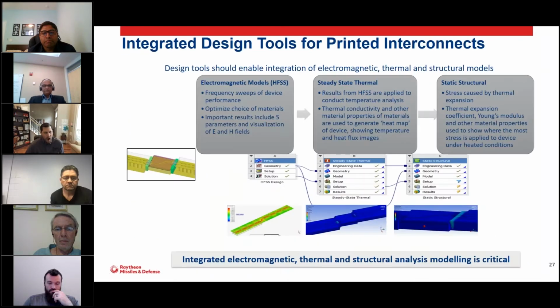And then once we've done that, there's more to it before we really start to print. So for example, if you see this picture over on the far left, one of the things that's critical to us, unlike in some applications, is that we often have die that get very hot, and they can't just be a surface mount part. They have to sit directly on a cooling surface, whether it be a heat spreader or a heat pipe, vapor chamber, what have you. So in order to make sure we have our best microwave properties, we don't want to build ramps up to the die. We actually have essentially a deep valley between the die inputs and outputs and the board that we're connecting to, whether it be laminate or ceramic.